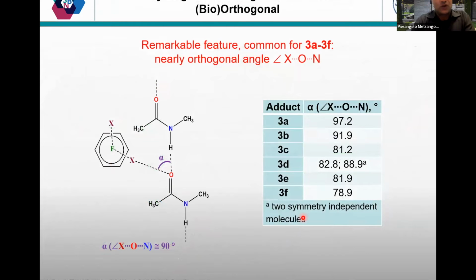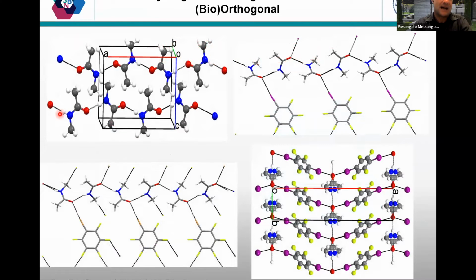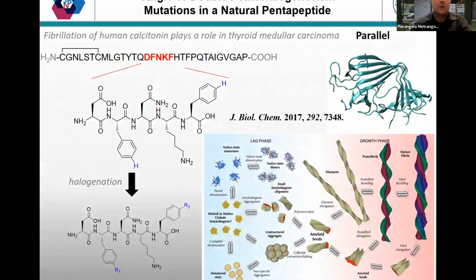So we also wanted to study the interaction of halogen bonds with peptides, and for this reason we studied this very, very simple model system, a model of the beta sheet made of N-methylacetamide, which also makes co-crystals with different iodo-tetrafluorobenzenes. So this is the hydrogen bonded chain of N-methylacetamide, and actually these hydrogen bonded chains interact in a perpendicular manner with the halogen bonded species thanks to halogen bonds, as you can see here. So actually the halogen bonds can interact with the beta sheets without disrupting them. This was the basic idea.